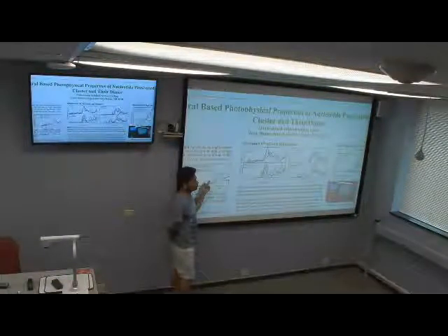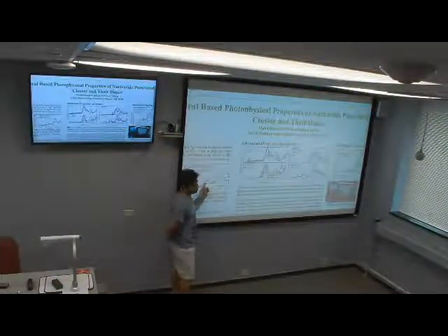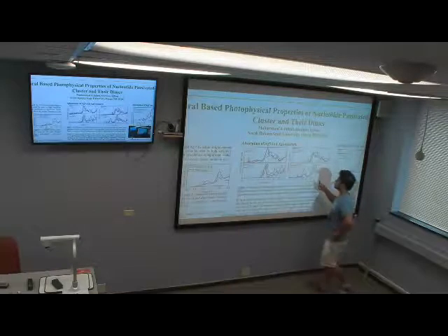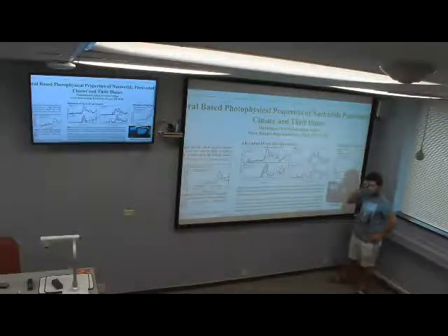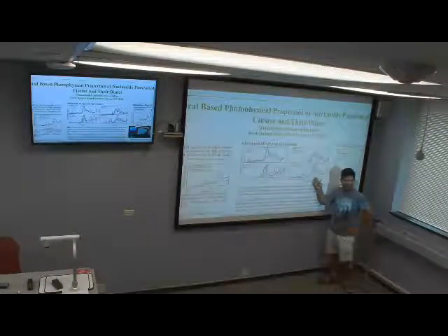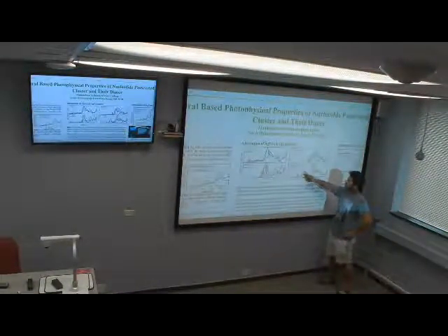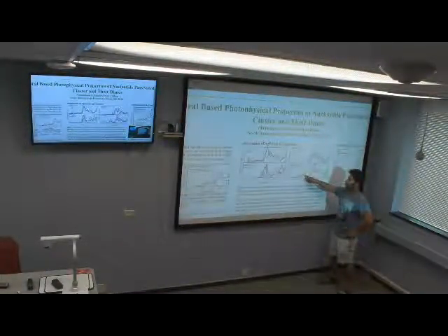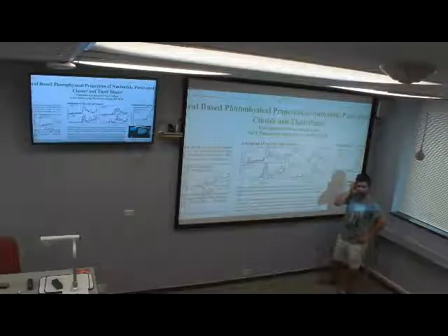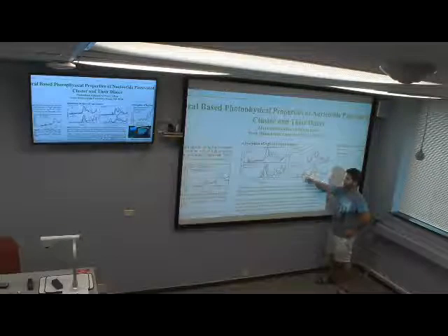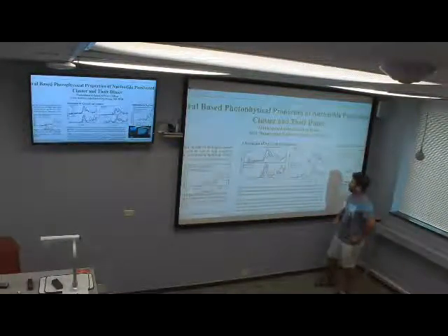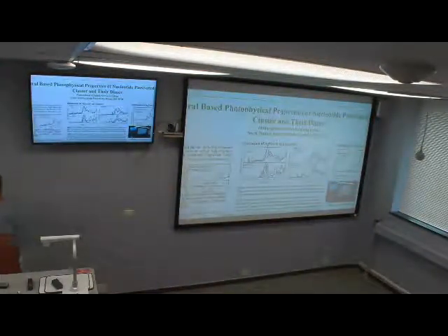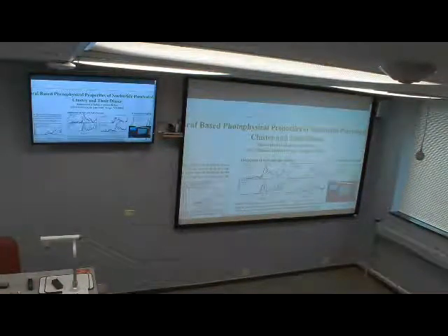Another thing is, if you remember the experimental one, we showed that the experimental group is mainly looking for the reason for increasing the intensity of the second peak and lowering the intensity of the third peak. So in the case of silver 6, this is the 1+ cluster, and this also has doublet conformations. If you look at the second peak, this red line, a mixture of guanine and cytosine, increases the intensity, but in the other two cases the intensity is almost the same. I mean in the cytosine and guanine ligands alone, but in the mixture of both it increases the intensity, and this one is also lowering the intensity compared to the other one. So this charged cluster gives us agreement with the experimental result.